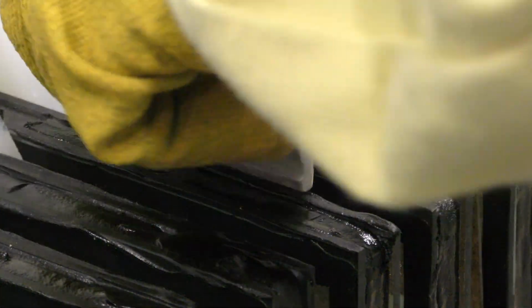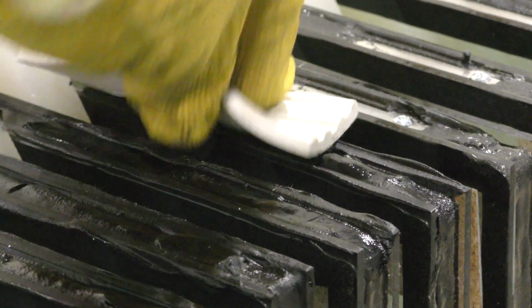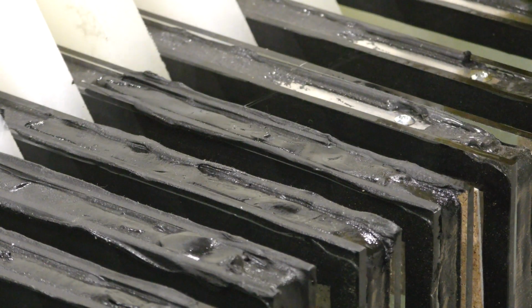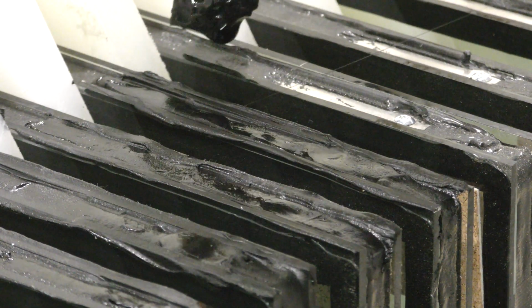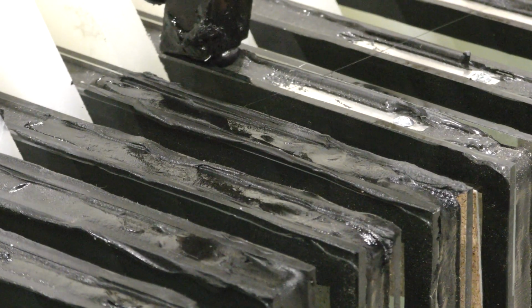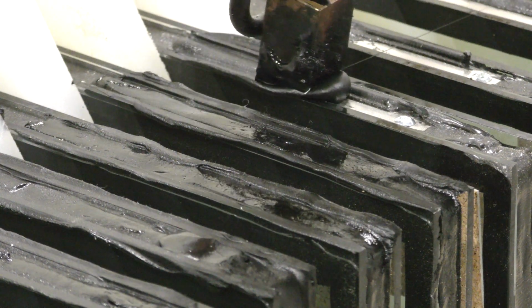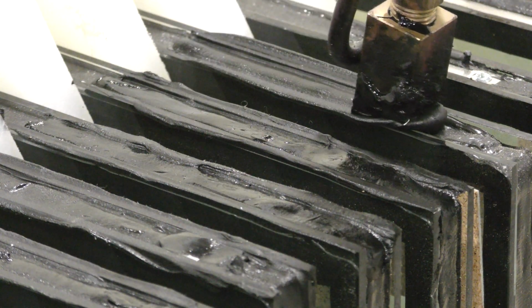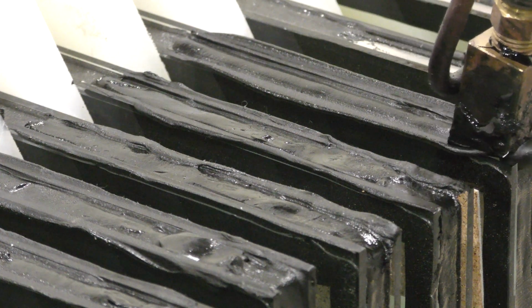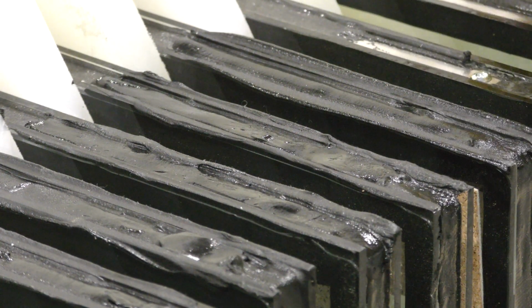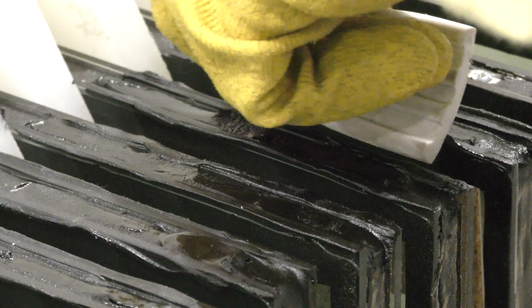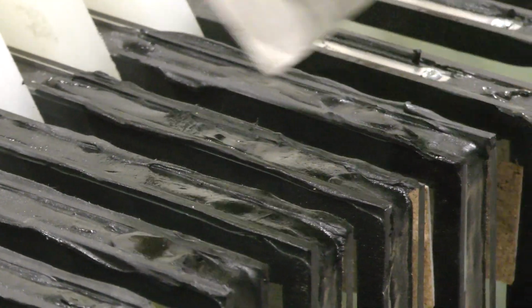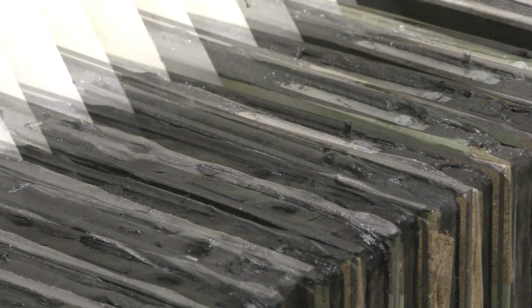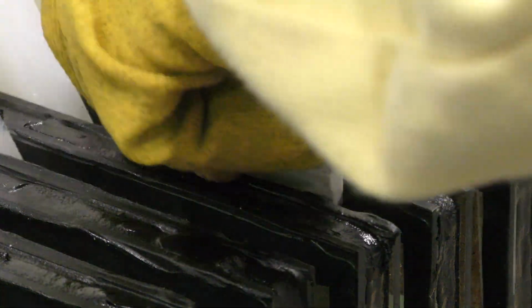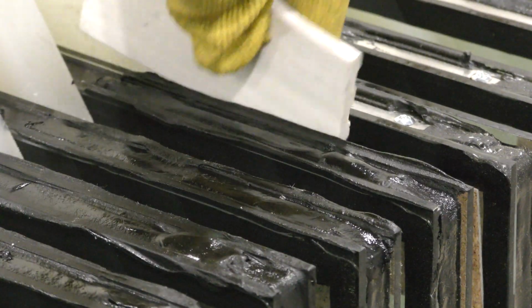While patching one unit at a time is best, never exceed 4 to 5 units at a time, as the material cools too quickly, resulting in a cold patch. Before the patch sealant has a chance to cool, the sealant must be pressed into the patch area. Using a silicone pad between the patch and the index finger, apply pressure to trowel the hot patch into the valley between the two lights of glass and around the corner.